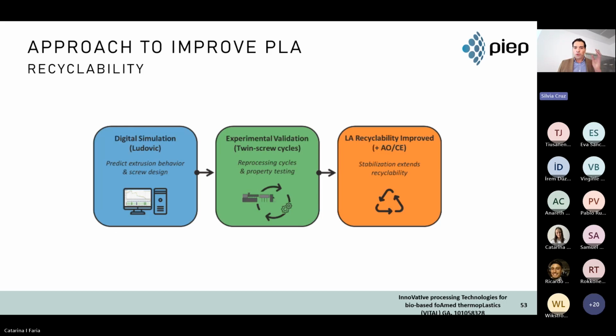So what was the approach, at least in Vital? We mainly focus on digital simulation. We use common commercial software for compounding, that is Ludovic. Together with it, we run some experimental validations on twin screw extruders, which are mostly used for compounding. So I would say we create loops between the digital simulation and experimental validation. And of course, in the end, we also try to identify the best approach to improve the recyclability of the PLA through compounding and through additivation. So mainly these three were the main steps that we had during the project.